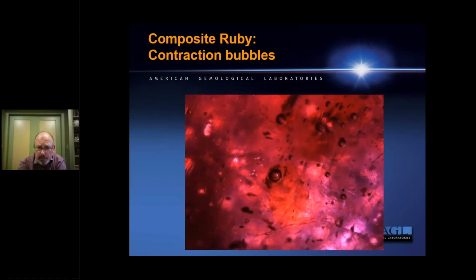You'll see gas bubbles. Now you have to keep in mind, when you see a nice spherical gas bubble, this is actually a contraction bubble, occurring in a much larger volume of this high lead content glass. If you look at the large spherical contraction bubble in the center of this image, you're going to see an orange coloration around here. This is all one big pool of glass inside the stone. And so all of these nice spherical contraction bubbles that you see are all part of a much larger pool of high lead content glass which is occurring in these stones.